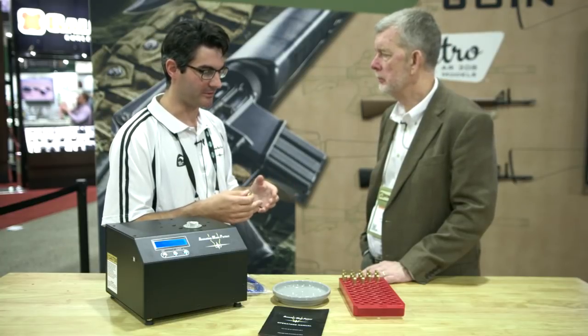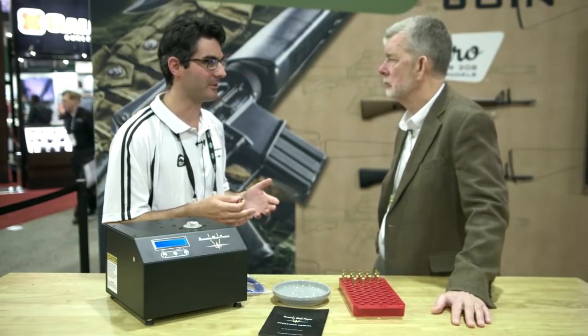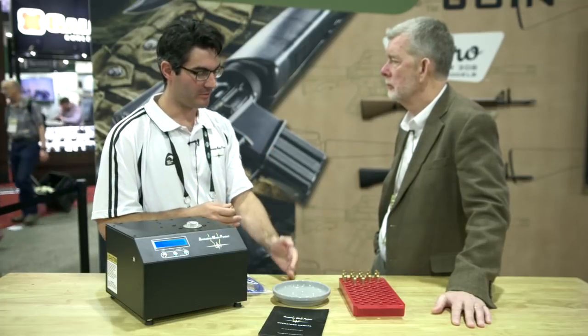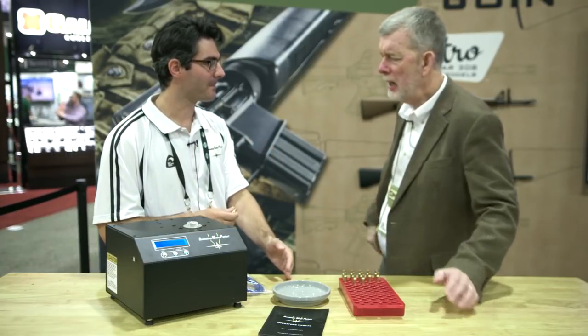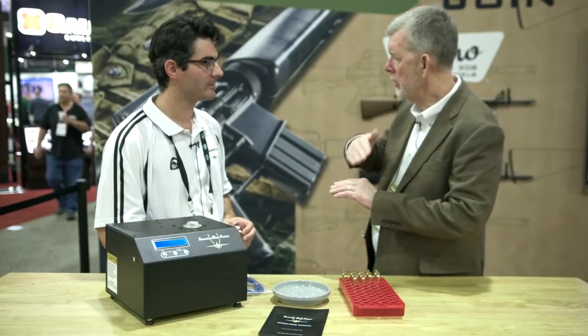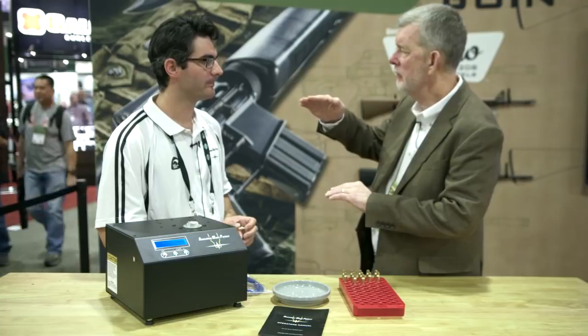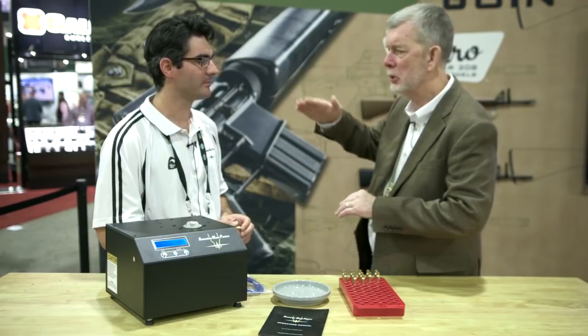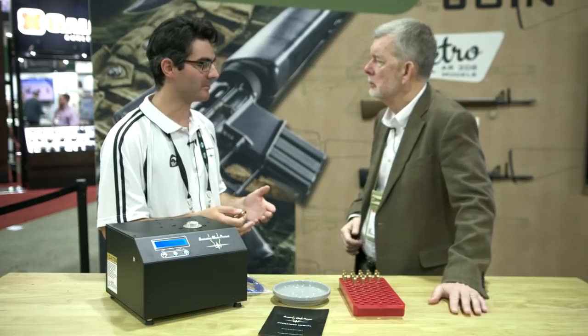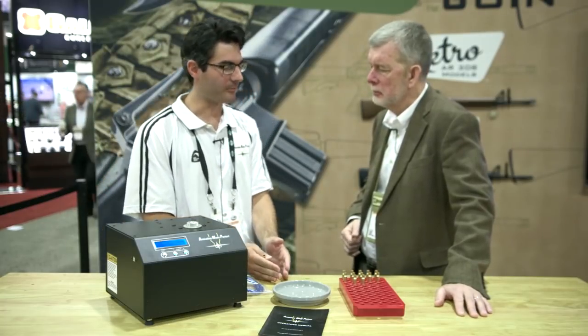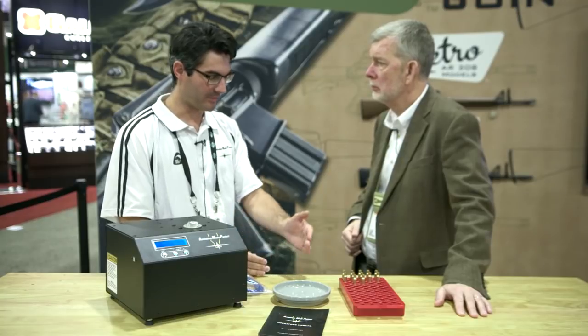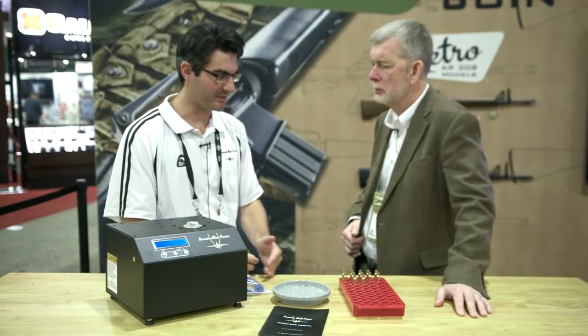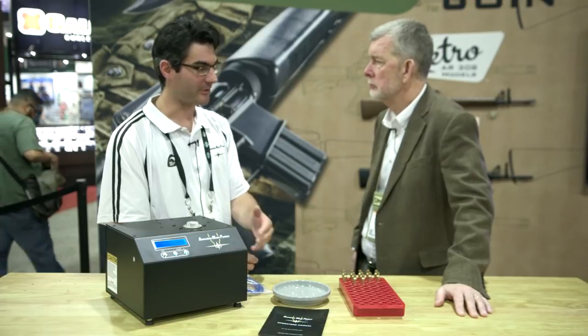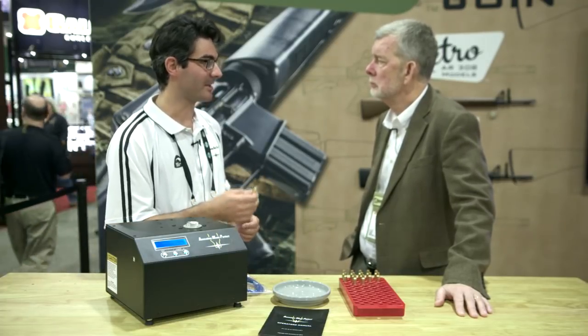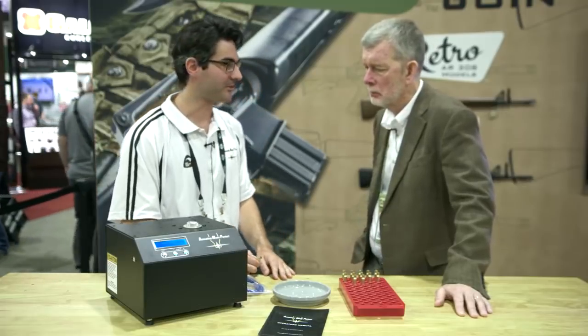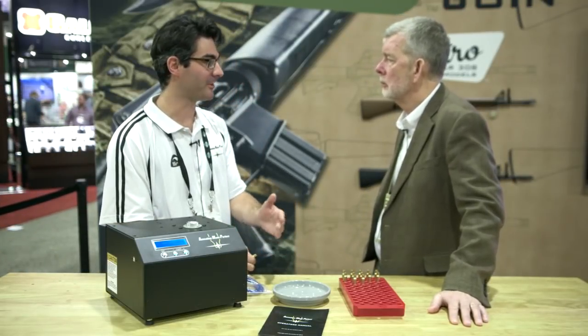People seem to have this idea that 750 degrees is actually the right temperature, but that depends on the time. I've heard a range of temperatures. When you try to look it up or Google it, you get anywhere from 500 to 750 to 800. Yeah, people are all over the road. So what no one has really done is find out the temperature time relationship for annealing. It's always been that this is the temperature, and however long you take to get there doesn't matter. Well, what we've discovered with our research is that it does matter. We found that temperatures can exceed 900, for example, if you're in the 5 second zone.